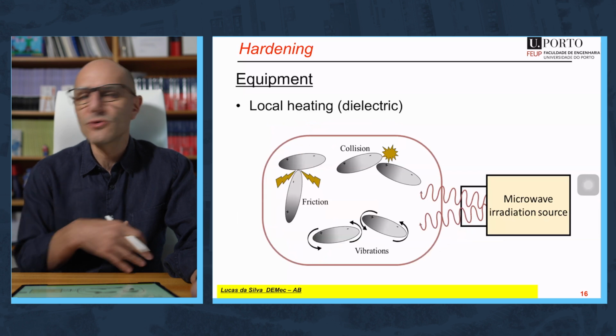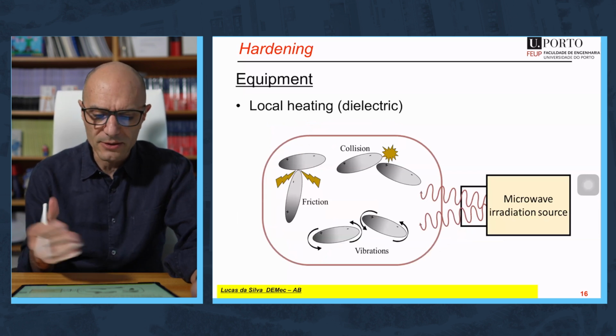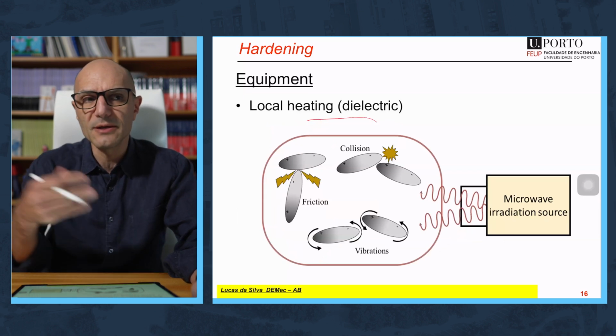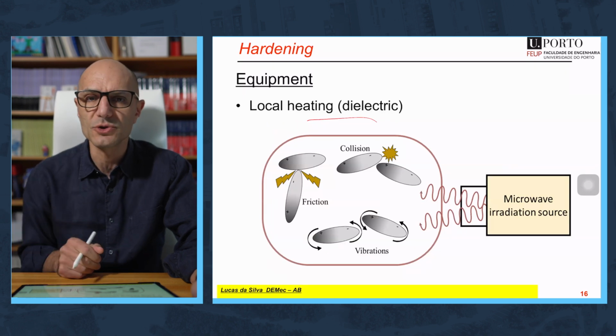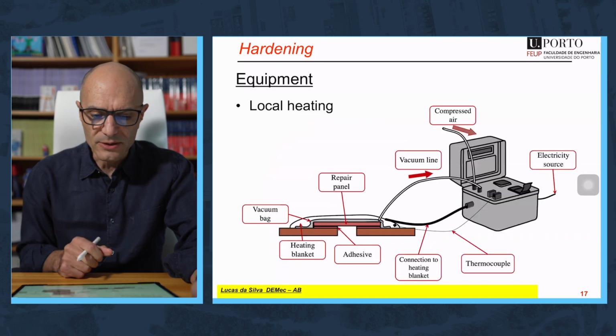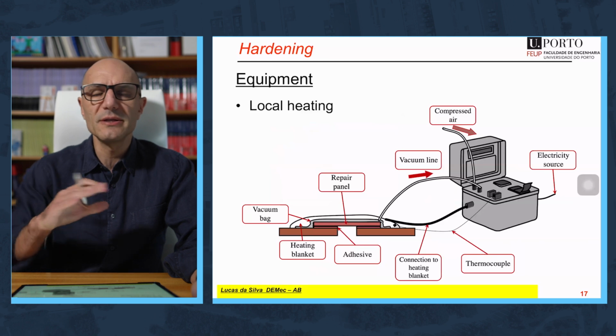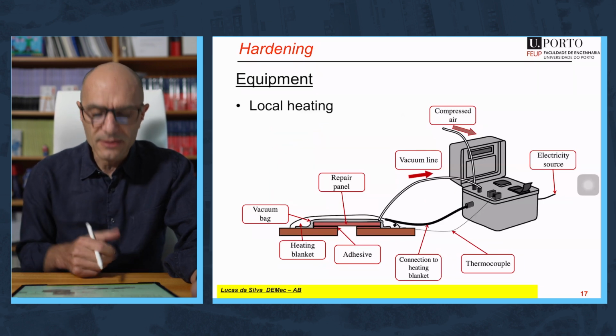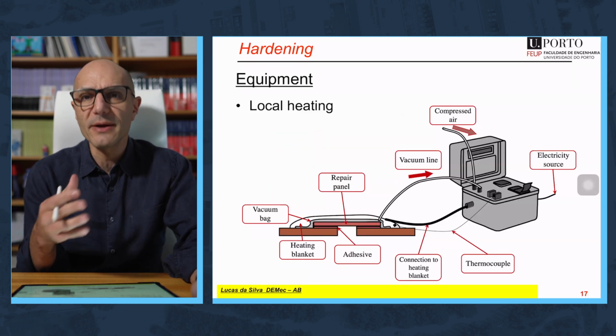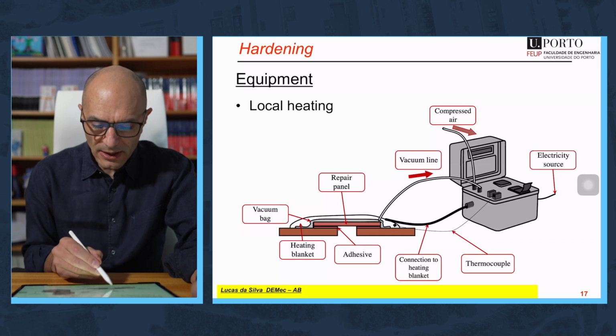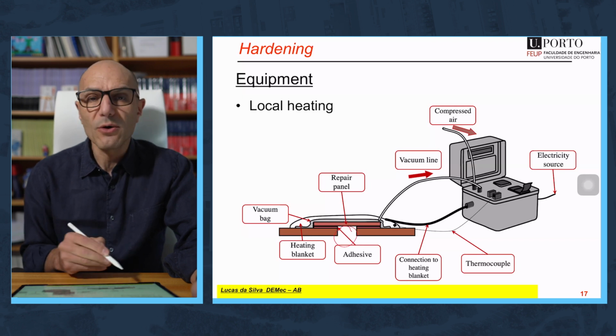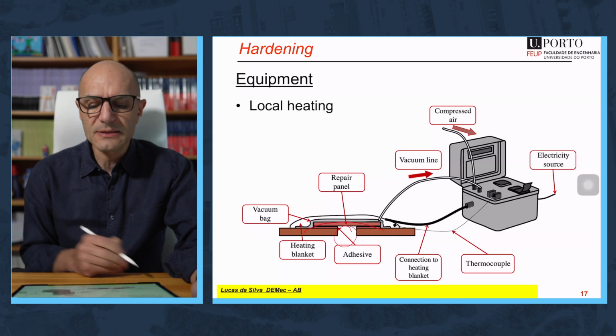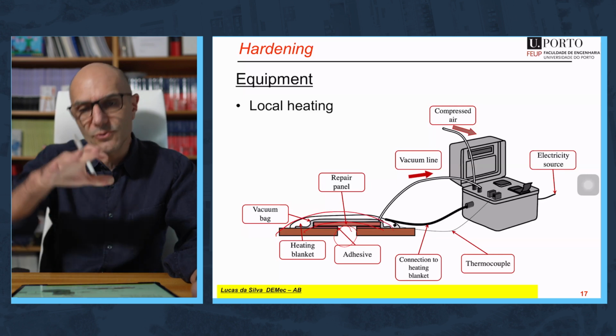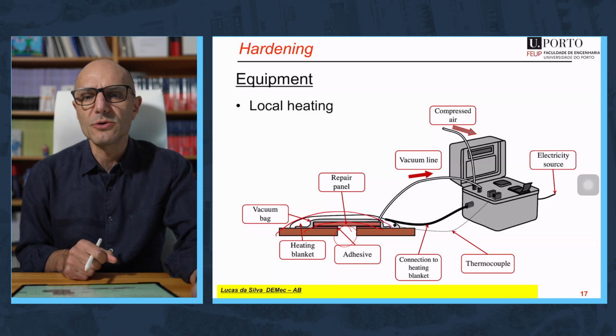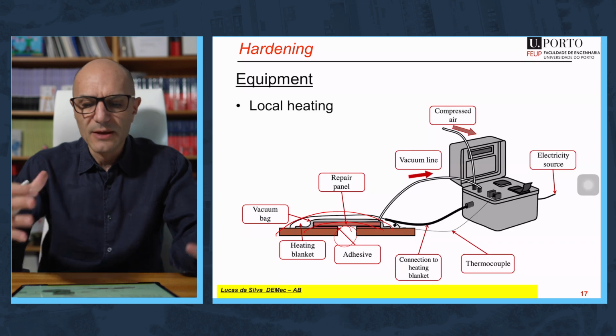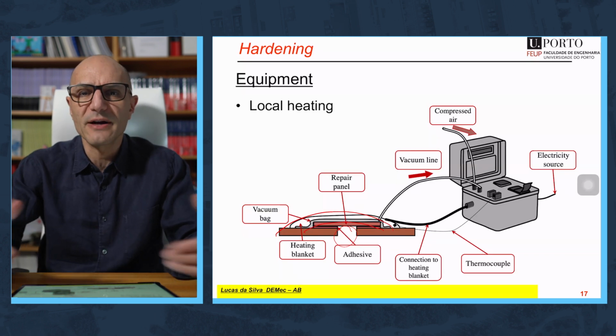For cases where you don't have conductive materials, you can use dielectric heating, microwave heating, for example, to join plastic materials. That works. And finally, you can also use a heat blanket. This is very common in repairs in the aeronautical industry, as indicated here. So imagine you have a hole, you put some laminates, and on top you put the blanket that would heat only locally the joint to be repaired. So that concludes the manufacturing part.